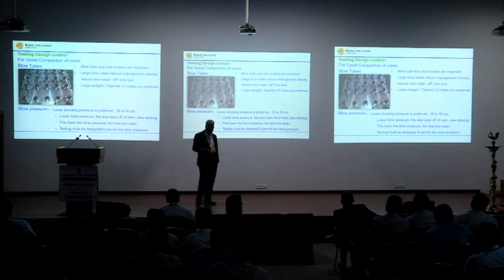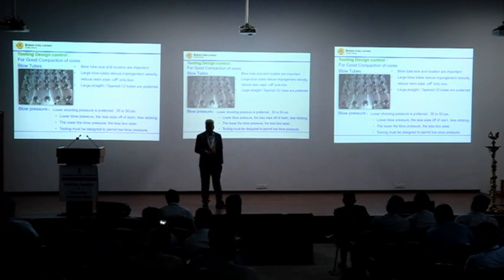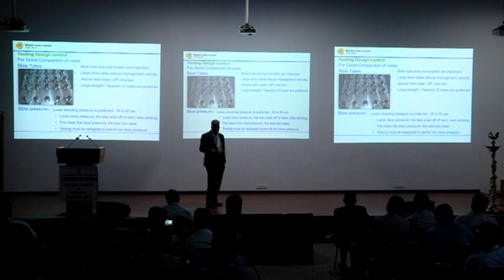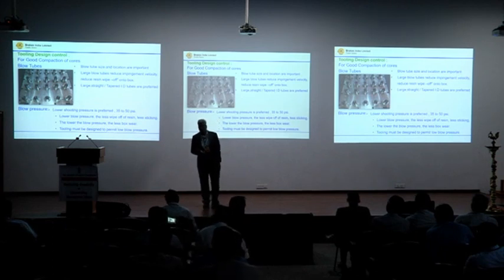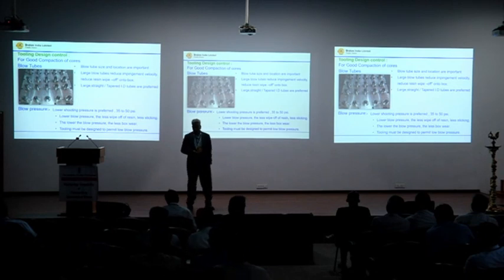Lower blow pressure is preferred because it reduces sand wipe up and sticking with the core box. Lower the blow pressure, less wear of the core box. Tooling must be designed to permit low pressure shooting, which is important to ensure at the design stage.